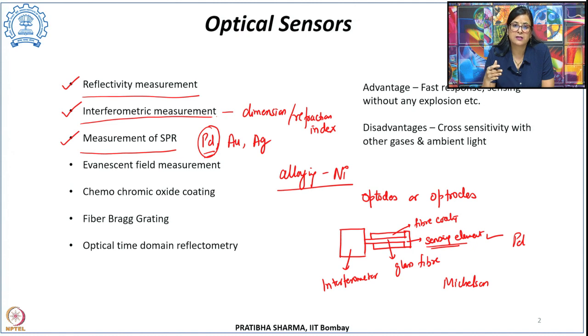Now, this delamination is a result of expansion that takes place on hydrogen adsorption, and repeated cycling, expansion and contraction, causes delamination. When we alloy it with nickel, it makes the film more stable. At the same time, we can also have alloying with other elements like gold or silver, and this increases the stability of the palladium film, and it also makes the response faster in the optical sensor.